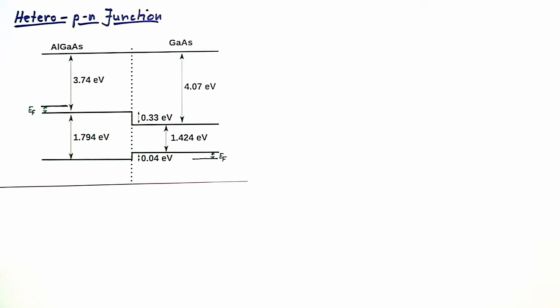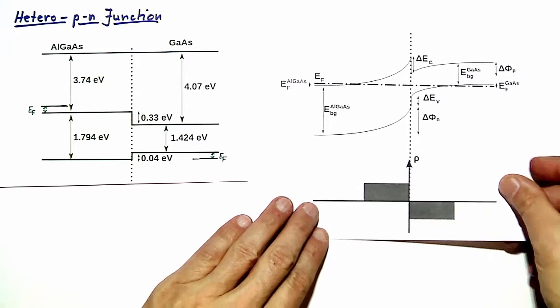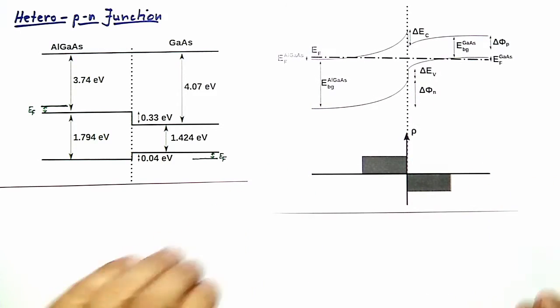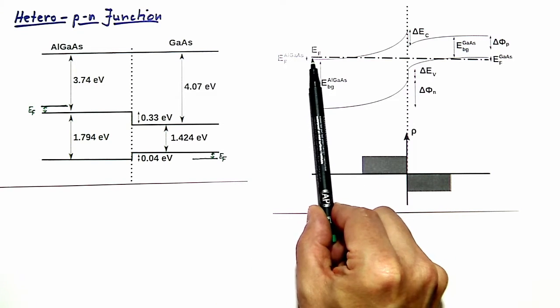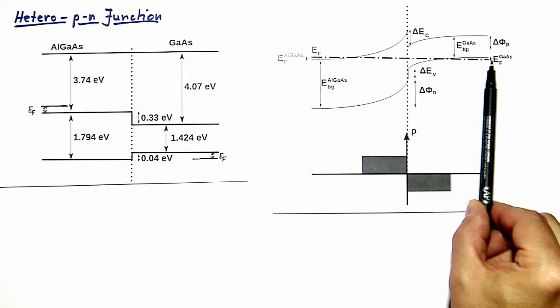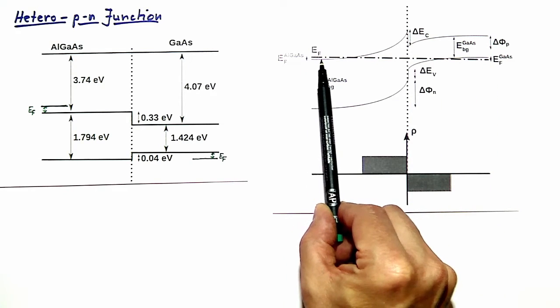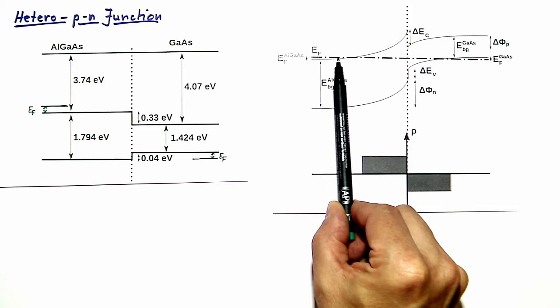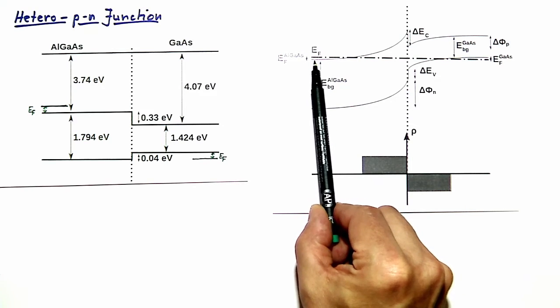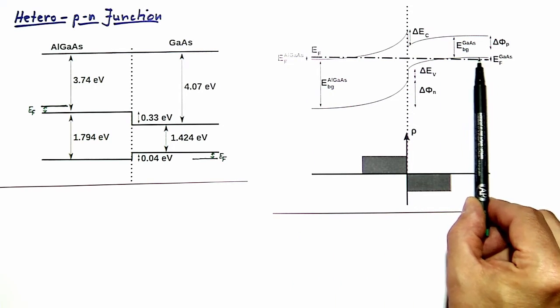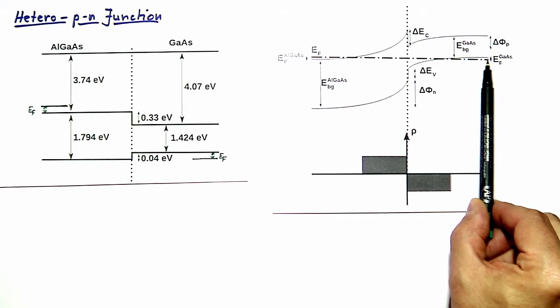I have prepared a sketch of that here. In order to get the electrochemical potential — shown as the dash-dotted line — constant throughout the structure, and have the aluminium gallium arsenide degenerately n-doped, meaning the Fermi energy is above the conduction band edge, the bands have to bend in this way.